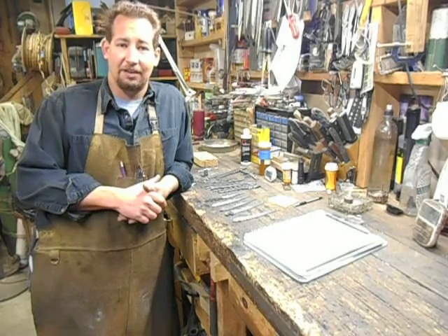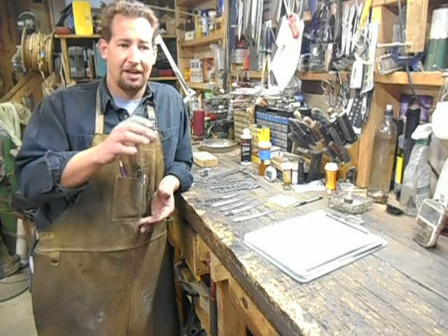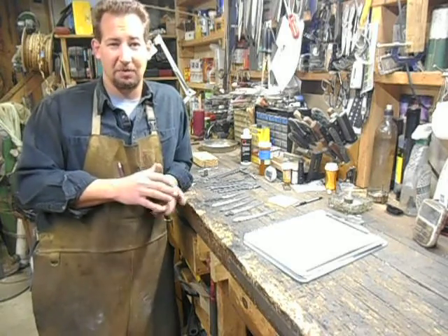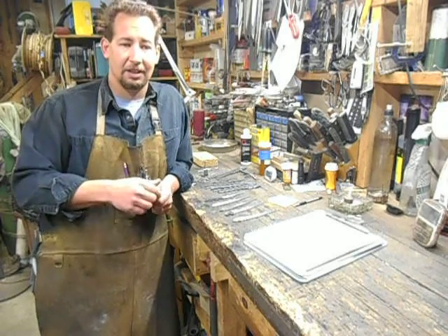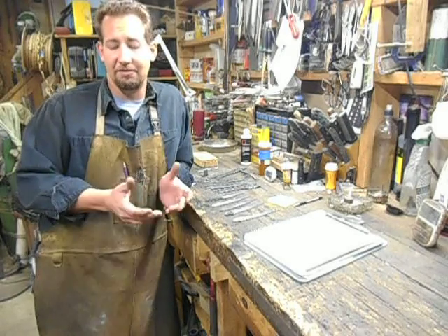And it really didn't work out very well. I've got that steel in there getting hotter and hotter — we're talking yellow, almost a little bit of white. The steel's looking runny and everything. Pull it out really fast, smash it with a hammer, let it cool down, break it — and the two layers came apart real easy.